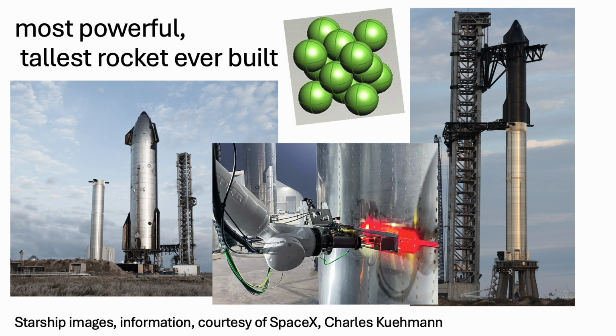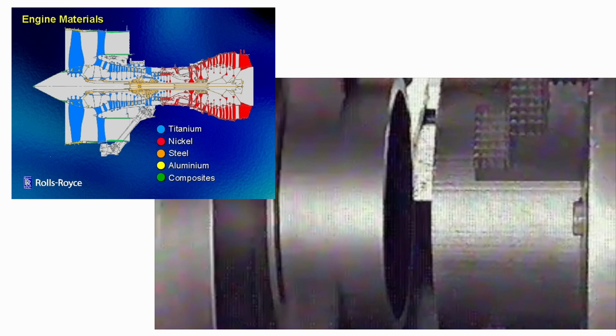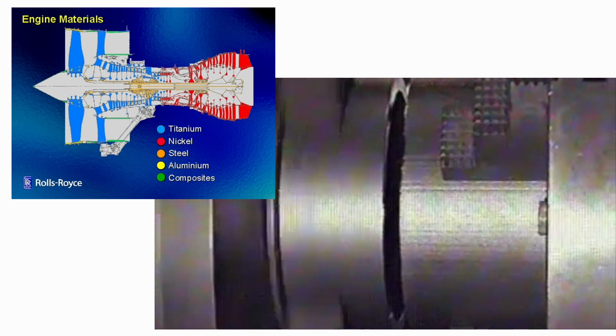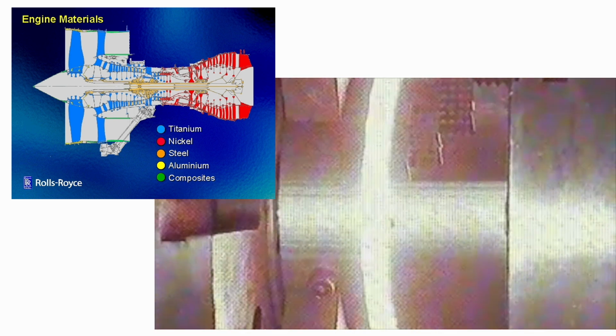And I'll give you another example in aero engines. So in aero engines, more than 10% of the material in there is steels. And one of the most important components is the shaft of a large civil aircraft engine. And that shaft is made usually from two different steels. One that can be very tough and doesn't experience too high a temperature, and the other end which is a creep resistant chrome moly type steel. And the two then have to be welded together using friction welding and then machining off to create a smooth surface.